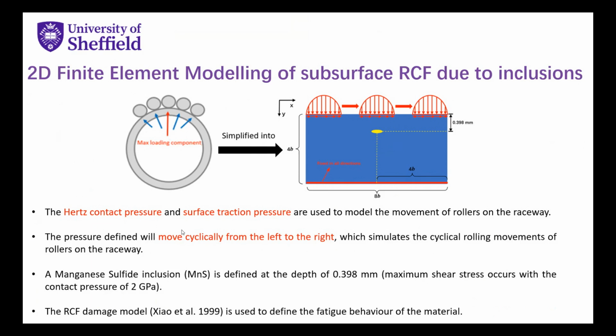And also I defined an inclusion, which is a MnS inclusion at the depth of 0.398 millimeters. This area is the area that maximum shear stress occurs with the contact pressure of 2 gigapascal, which is the rated pressure on the bearing. So in the end, I use the damage model to define the fatigue behavior of the material. This damage model comes from a published paper in 1999.